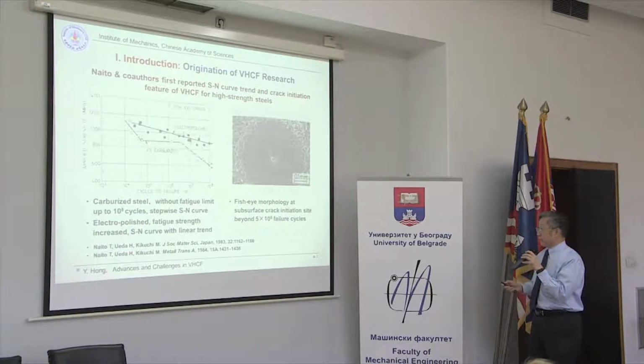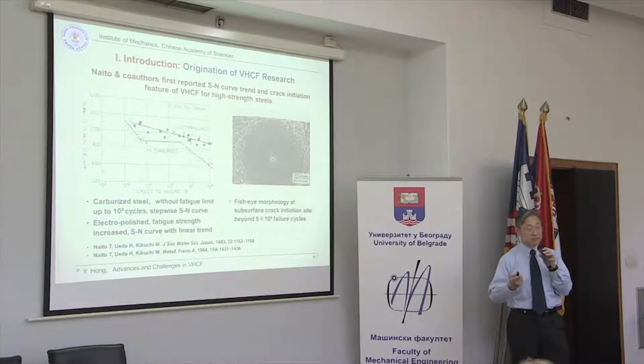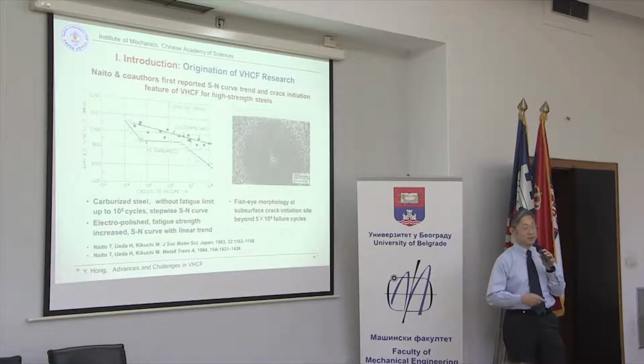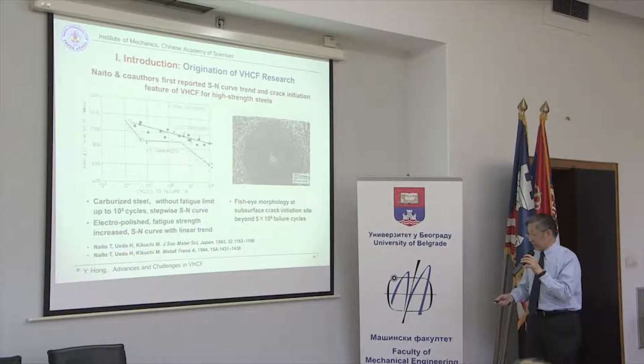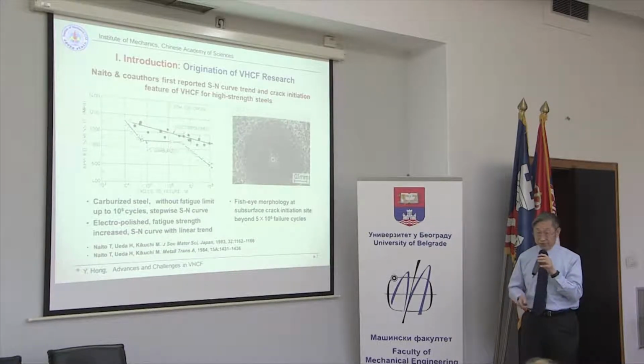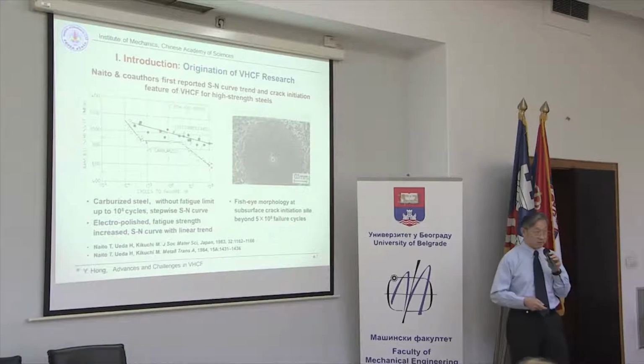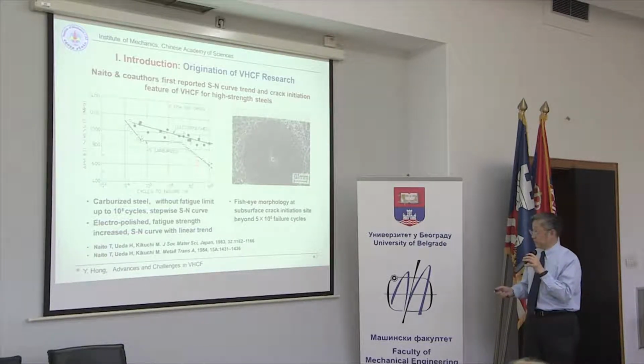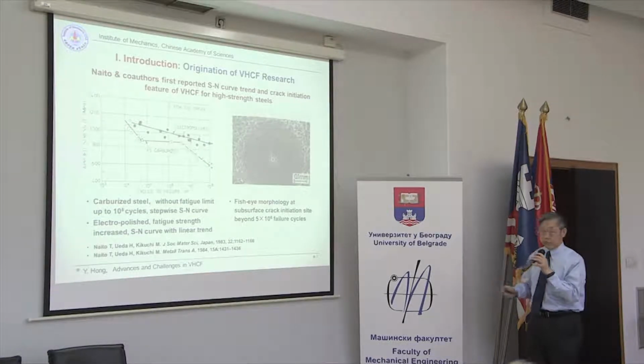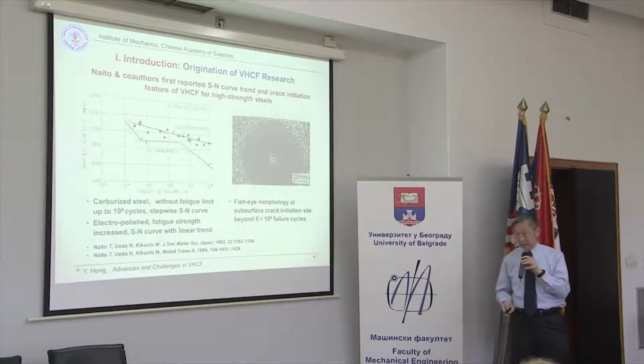And then I would like to mention the origination of very high cycle fatigue research. I said conventional fatigue is the fatigue behavior less than 10^7 cycles of loading, but very high cycle fatigue is beyond 10^7 cycles of loading. And the origination of very high cycle fatigue is about 35 years ago. This is an example for high strength steel to show fatigue failure may happen after 10^7 cycles of loading. And this example shows crack initiation from the interior of the specimen.